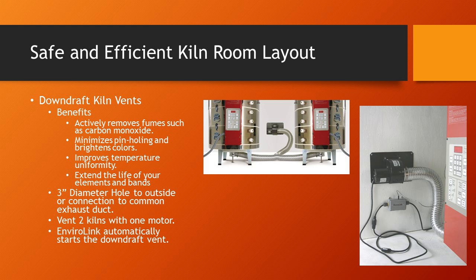It also, since you're bringing more oxygen into the firing, if you have troubles with pinholing, and I know a lot of you guys are using commercial bisque, but let's say you get some bad bisque and you don't want to have to send it back because you're getting a ton of pinholing, you could refire that bisque and burn out all the carbon in it, because what's happening is the carbon is not getting out when it's fired in the factory, and then it comes out and causes pinholes in your glazes when you do your glaze firing. It also improves or brightens colors because you're getting more oxygen in there.